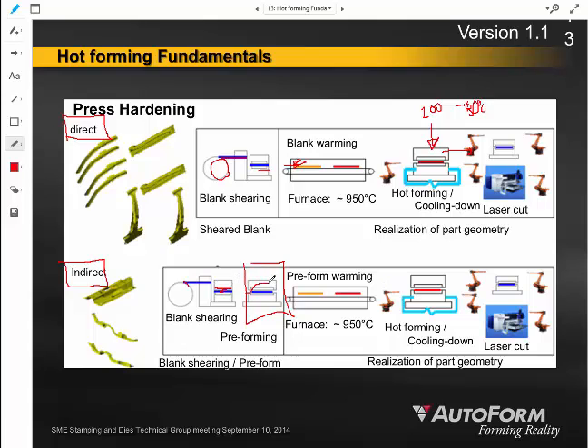If we do the preforming at ambient temperature initially, that allows us to do a little bit of initial stretching of the material and hopefully be able to maintain a relative uniformity or at least less localized thinning behavior. Then we can put it through the furnace. So take the preformed thing and now heat it up in those furnaces to 950 degrees C. Then stamp it even more in this temperature controlled die in order to quench it, and then go to the laser cutting. And that would be indirect hot forming.